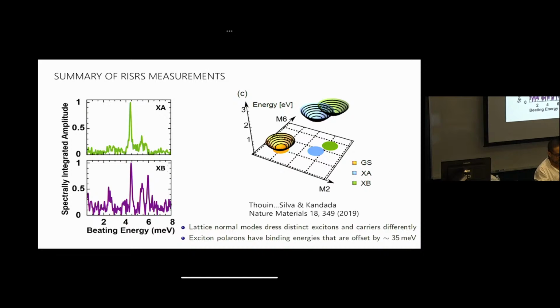That doesn't show that they're exciton polarons. The other models that I talked about briefly, you would also see this, but each of these excitons are dressed distinctly by the lattice and distinctly from the photocarriers. Okay, so this supports the exciton polaron story. You might have exciton polarons. We haven't proved it, but certainly this data is consistent with that.